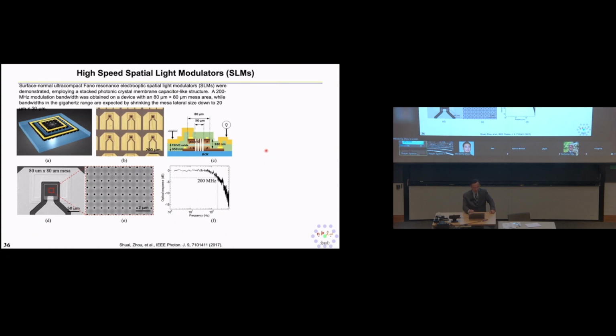This one demonstrated amplitude modulation, the same as the one I showed before, a double lattice photonic crystal structure, essentially a filter. That means light passes through with a certain resonance. If you modulate the refractive index of the material, silicon, you can tune the resonance away. So if you shine a single wavelength of light, your resonance is shifted on and off away from the wavelength of the light. In this case, you can modulate the intensity of the passing beam, and you can get very high speed modulation. Without much optimizing, we get a few hundred megahertz already, which is already much higher than